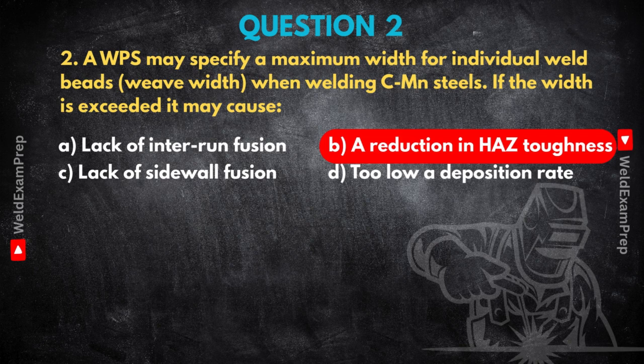Yeah, and just to touch on the others quickly, lack of fusion, inter-run, or sidewall, that's usually more about technique, travel speed, angle, maybe not enough heat overall, rather than too much heat from a wide weave. And a wide weave certainly doesn't mean a low deposition rate. If anything, you might be putting down more metal per pass. So yeah, the primary worry with exceeding weave width in these steels is definitely that hit on HAZ toughness. Okay, that makes perfect sense, the impact on the material's core properties.